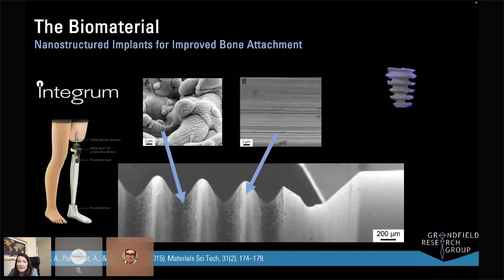So we wanted to look closely at this nanostructured implant surface in bone. And in order to do that, we need to make a small sample. The transmission electron microscope will only allow us to have a sample about 100 nanometers thick. So we need to use another microscope first to create a specimen for the TEM.